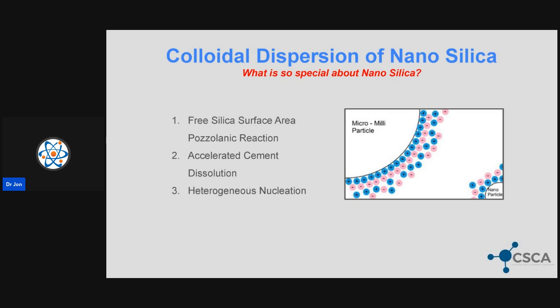Because you have that accelerated consumption of calcium hydroxide to develop more of that strength-bearing structure of concrete, the calcium silicate hydrate, you have a higher degree of cement dissolution. We call that accelerated cement dissolution. Two great papers, Bjornström et al., back in 2003 and 2004. What that basically means is we're getting a higher dissolution rate. We're getting more bang out of one cement particle compared to what we would get without that nano silica technology.